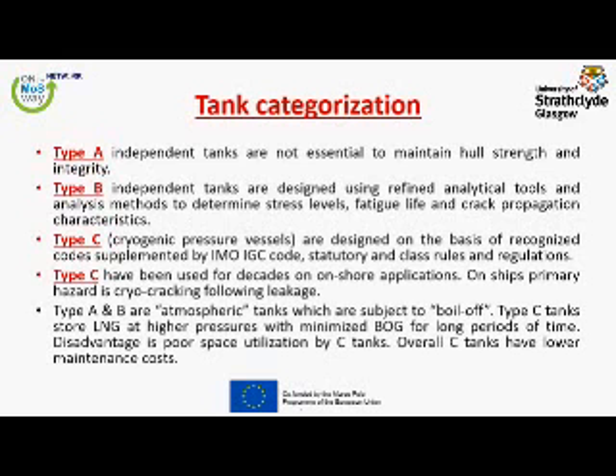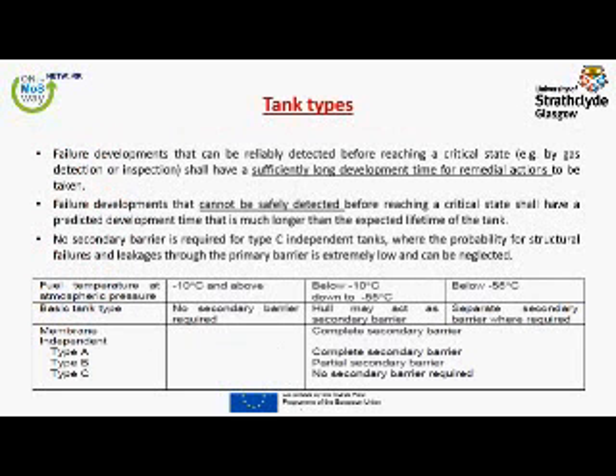But what is the disadvantage? I will agree with yesterday's speaker that the space utilization of type C tanks is poorer. If we have some failure that we will not be able to detect in future inspections, we need to ensure that this critical state will not degrade to failure for the lifetime of the tank. So if we have a crack, we assume that the weld will have an initial defect, and this defect will not propagate to a critical size for the lifetime of the tank.